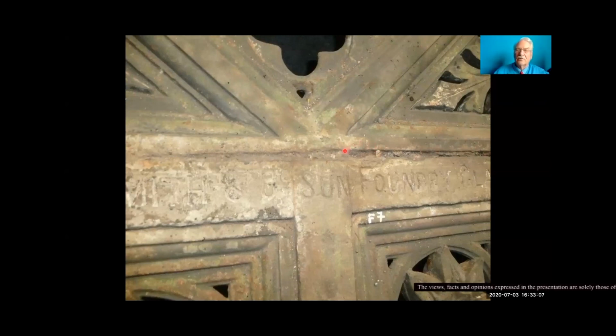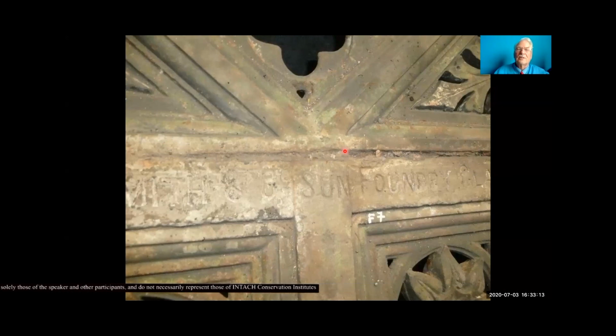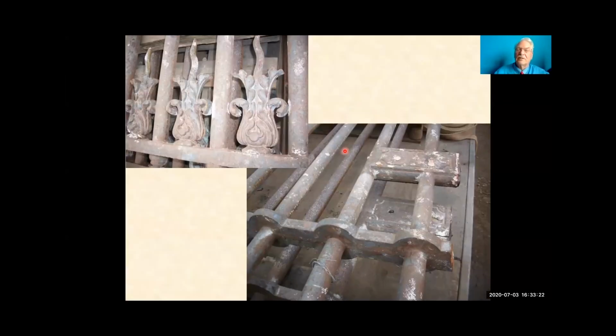So it worries me. You have to pressure wash very carefully, preferably just soak in water to try and wash out any of these chemicals, and then thoroughly dry. But it is very non-destructive, provided you can get the material out afterwards. You can see that it might not work right down into the little tiny re-entrant places, but generally it's very good. And if there are marks, sometimes you'll see setting out marks from where the founder has been marking up, or the blacksmith maybe was doing some setting out with chalk. Sometimes these marks will survive if you take off the paint through a dipping process.